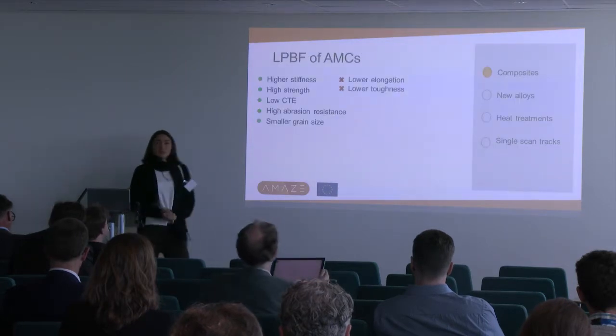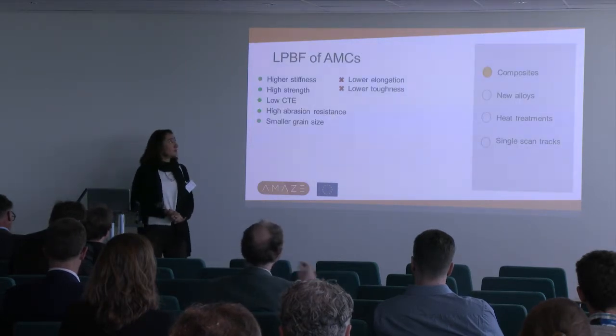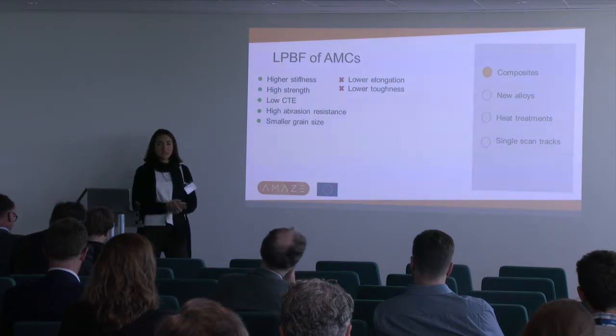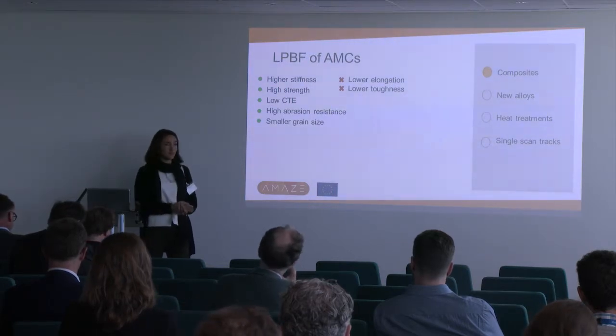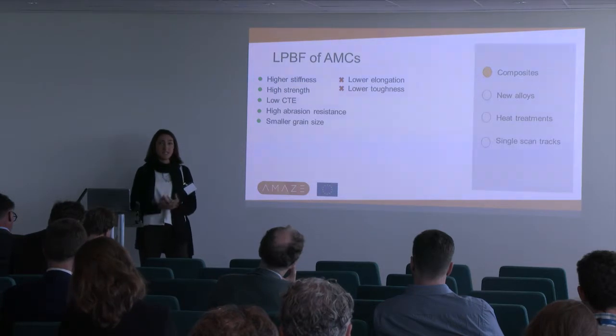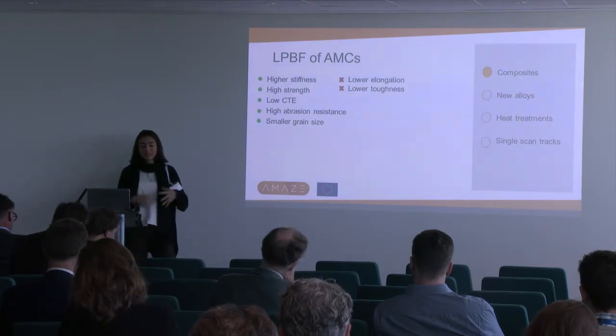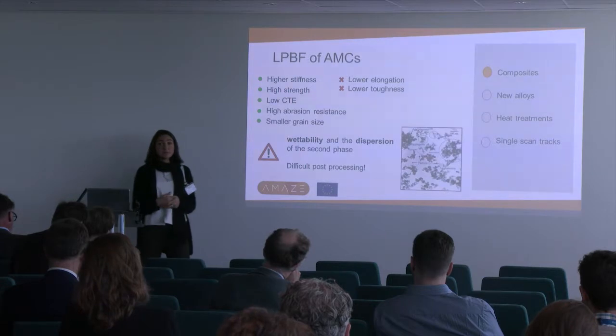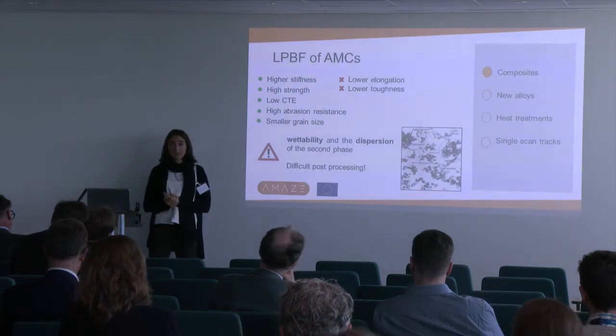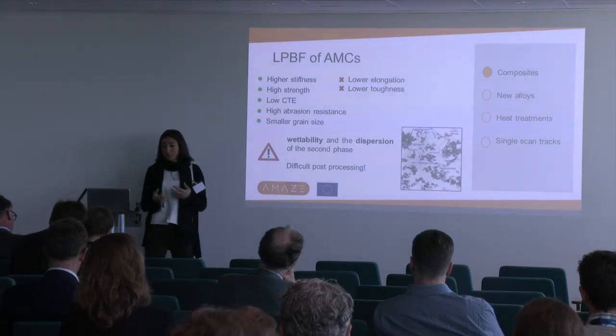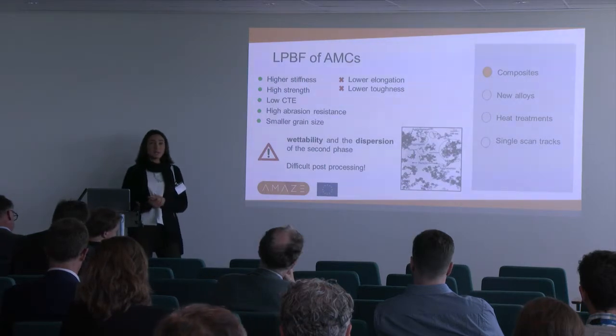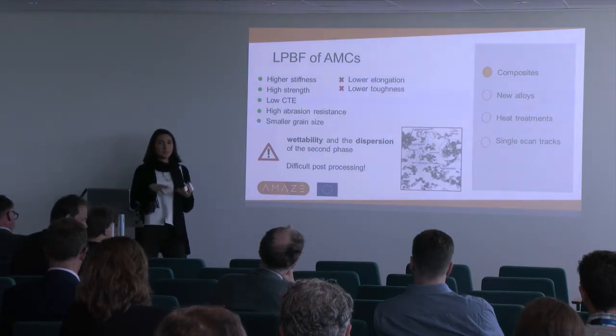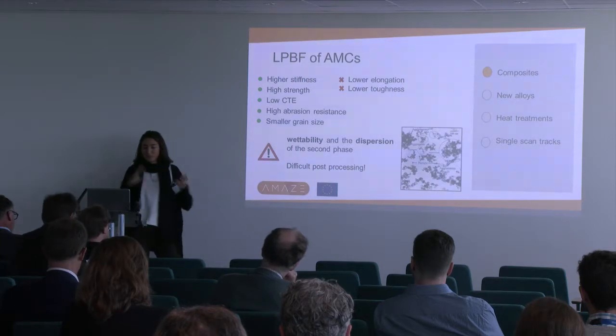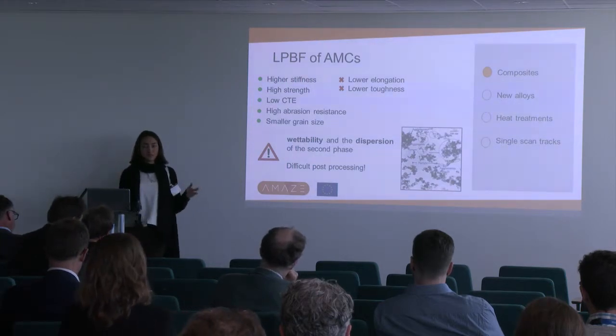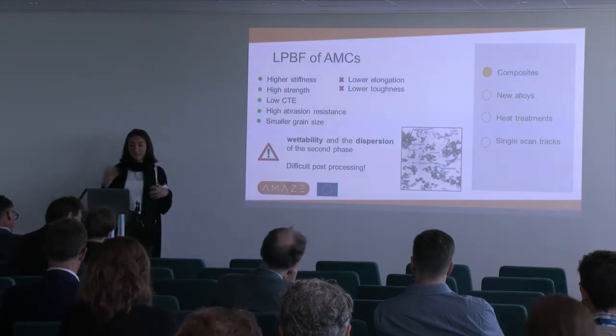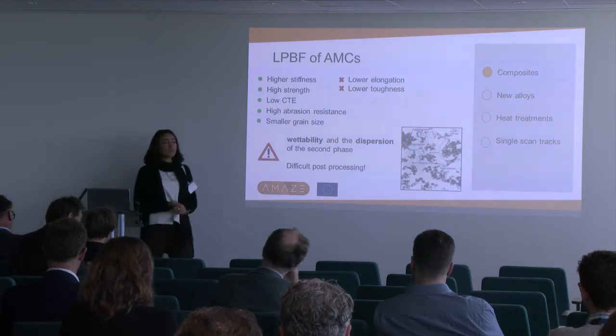So why produce composites by additive manufacturing? Composites have a lot of advantages from a mechanical point of view. They have high stiffness, high strength, low CTE, etc. But when we produce composites with conventional production technologies, there are many problems related to the wettability of the particles. So the particles do not wet and do not disperse homogeneously in the part. And also they can agglomerate, and the composites also have difficult post-processing.